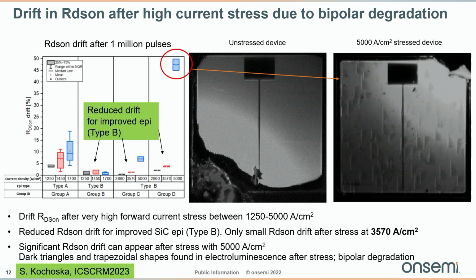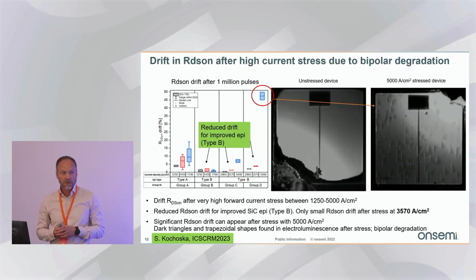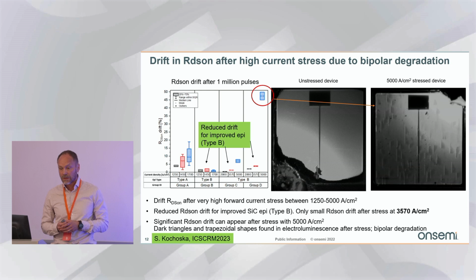So you can see when we improve the epi a little bit, what's called type B here, then we could suppress the RDS-on drift. This is after 1 million pulses, so we get a really small RDS-on drift, even with 3,570 amps per centimeter squared current density stress with 1 million pulses. But when going to 5,000 amps per centimeter squared, then we eventually see a strong increase of RDS-on.